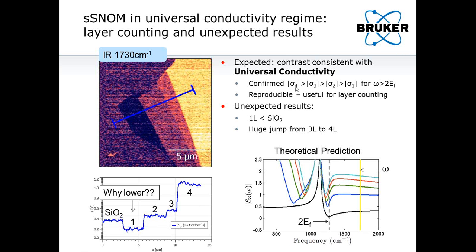We see that the conductivity of the 4-layer graphene is monotonically higher than the conductivity of 3, 2, and 1, and so on. And this applies if we're in the universal conductivity regime, which we know we are because the frequency we chose, 1730 wave numbers, should be much higher than twice the E Fermi.